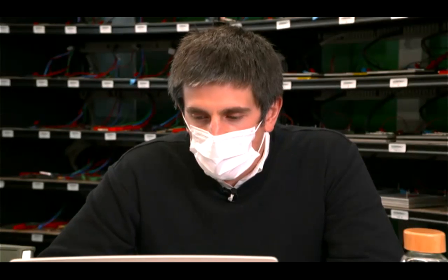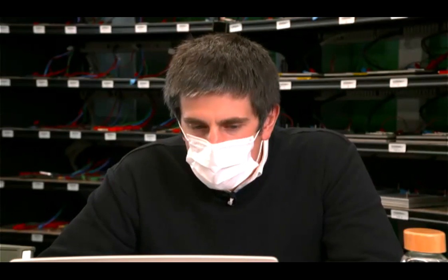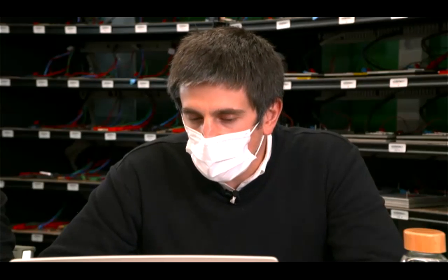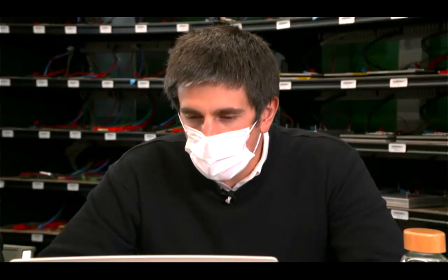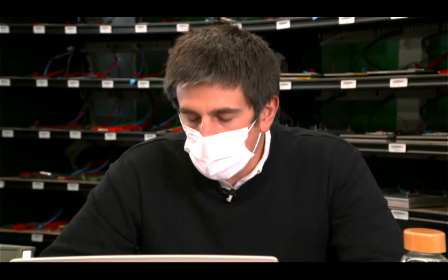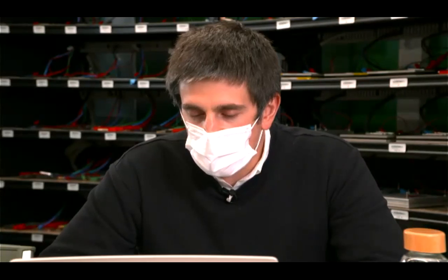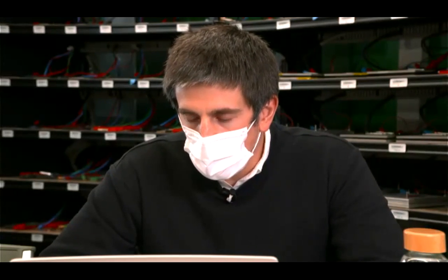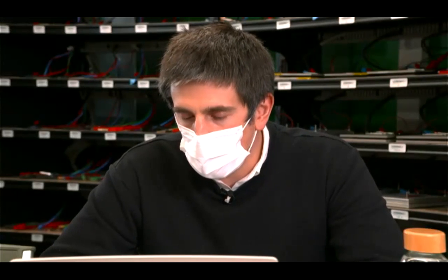Okay, so there's a question regarding when and how the pouch cell is finally sealed after the electrolyte insertion. If you remember during the video, first of all, we take the stack and we put it inside the electrolyte filling machine. From that part, we have the cell already sealed with this excess of pouch bag. Then, as my colleagues saw in the characterization part, they put it into the plates with this extra part that is taken out from these plates, doing the formation cycle and the generation of gases.